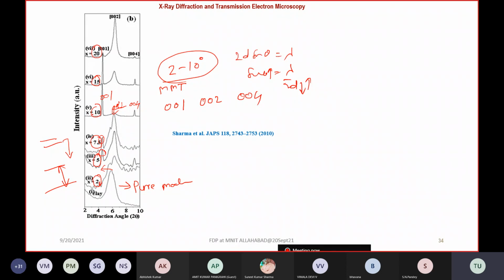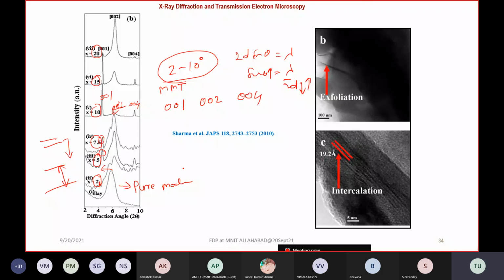So the confirmation is to be done by transmission electron microscopy. If you see the forward concentration, actually you are getting this peak coming. For that concentration, transmission electron microscopy gives these signatures. These are the channels which are to be seen, and this is around 1.92 nanometer. So these types of channels are going to appear, and this is said to be the intercalation.